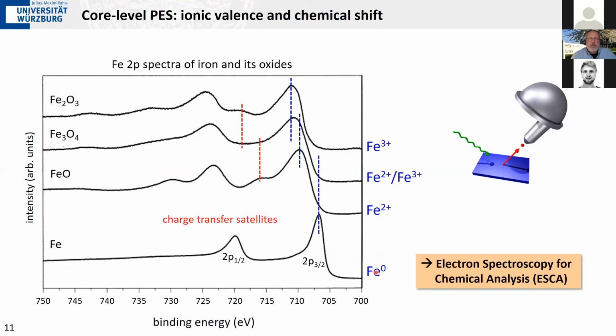In the metal we have neutral iron atoms. In iron monoxide, we have basically iron 2+. In the sesquioxide, we have iron 3+, and magnetite happens to be a material where iron can adopt two different valencies, 2+ and 3+. And as you can see here, the precise number of the binding energy increases as the valency increases. And also, you see that the line shape changes a little bit.